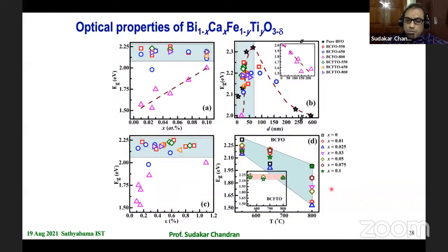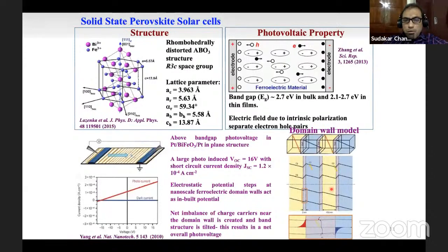So we have chosen an optimized band gap, the lowest size that we can get, and we tested the photovoltaic properties. So the photovoltaic cell that you would make would be all solid state in this case, because BiFeO3 is known to show very large open circuit voltage, and for example, the domain walls are shown to play an important role in getting very high open circuit voltage, because this particular solar cell works in a different way than the silicon solar cell works.